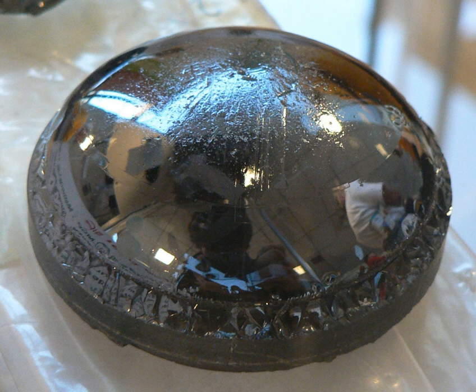A major problem for SiC commercialization has been the elimination of defects: edge dislocations, screw dislocations, both hollow and closed core, triangular defects and basal plane dislocations. As a result, devices made of SiC crystals initially displayed poor reverse blocking performance, though researchers have been tentatively finding solutions to improve the breakdown performance.